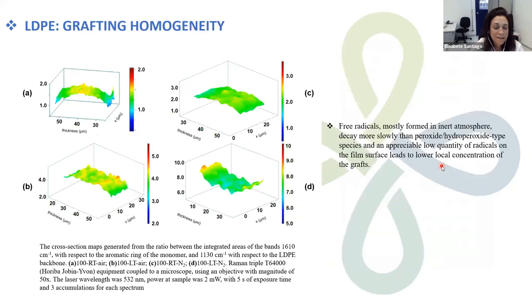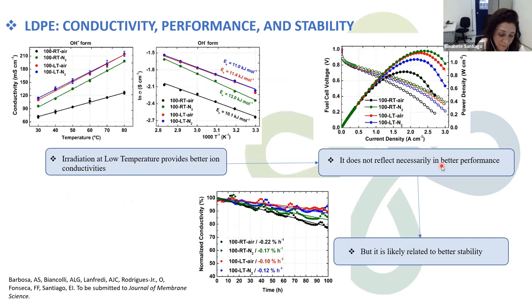So in terms of homogeneity, you have observed that atmosphere and temperature also have an effect on the grafting distribution. Samples irradiated under nitrogen lead to more homogeneous resulting membranes. This feature is likely due to the presence of free radicals, mostly formed in inert atmosphere, that decay more slowly than peroxide and hydroperoxide type species, and an appreciably low quantity of radicals on the film surface leads to a lower local concentration of the grafting.